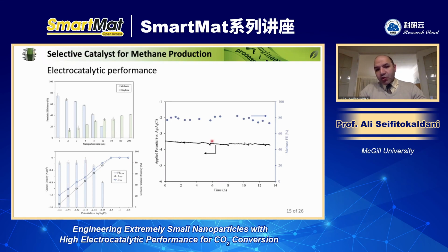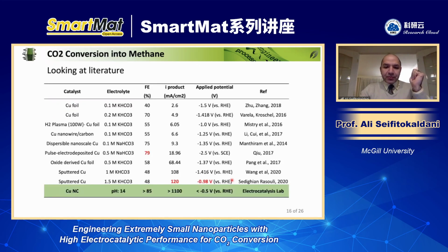And we were able to run the system for around 14 hours. Unfortunately, we are not able to run it further. One reason is the particles are very small, which makes it quite challenging to run for a very long time. So again, coming back to this table, now using our extremely small copper that we call nanoclusters,